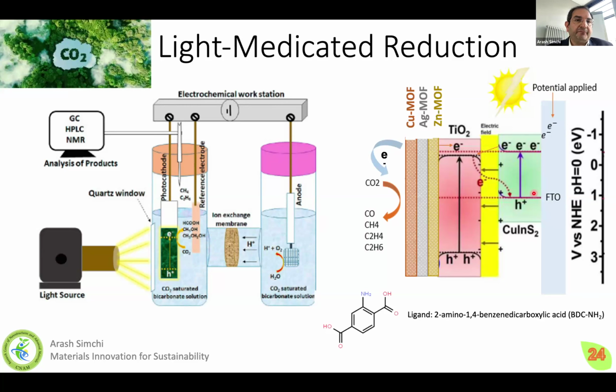As you know, it's a very famous material in solar energy systems. And then we deposited a thin layer of titanium dioxide on top, and 3 layers of metal-organic framework, MOF, which are coordinated metal polymer systems. With such a complex layer structure, we show that by irradiating the light, depending on intensity, we can have different products without changing our